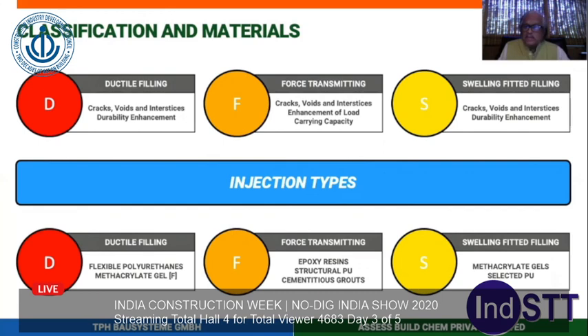Force transmitting means where there are structural cracks, where you used to use only epoxies, and due to the limitations of epoxies, in the conditions where there is water in the concrete today, there are structural polyurethanes which can be injected, which are more flexible compared to epoxies. So this can also be used for repairing the girders of bridges where there are vibrational loads. And finally, for swelling or just for filling, you can also use foamed materials, which are either gels or silicate foams or polyurethane foams.